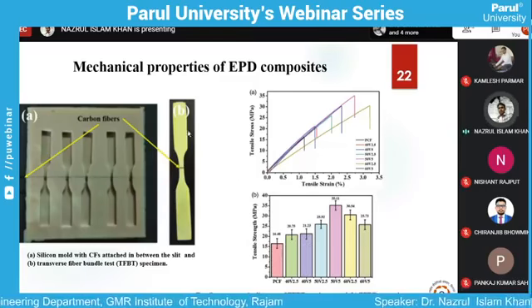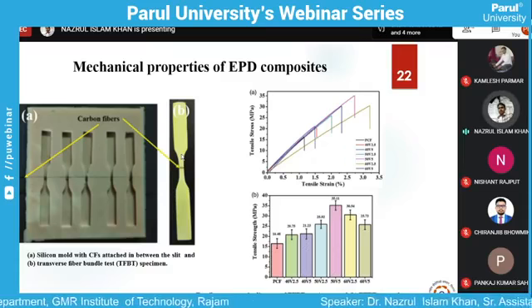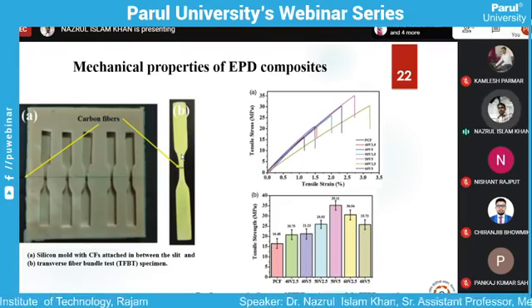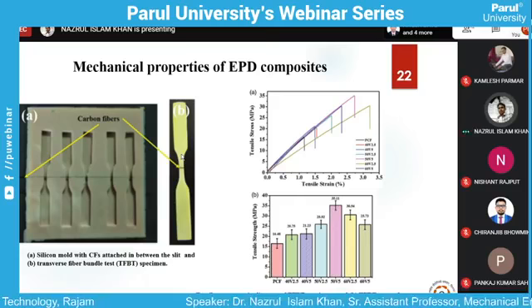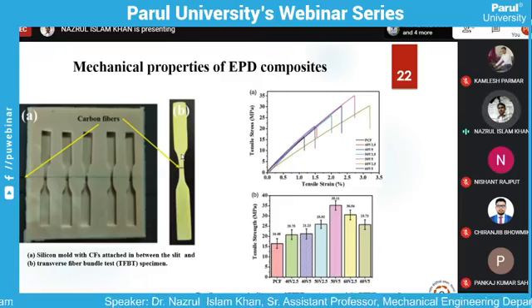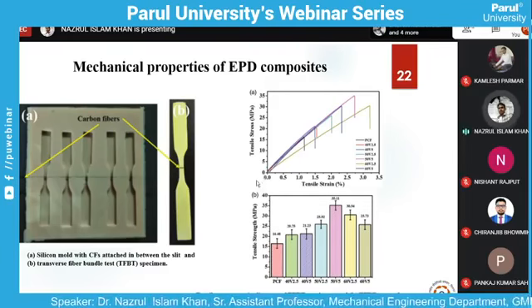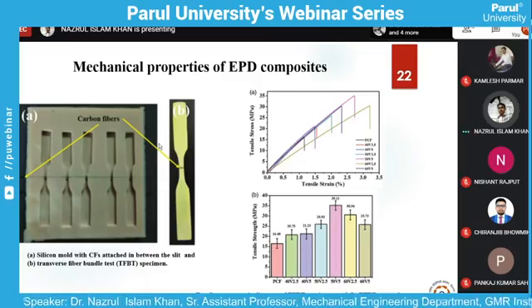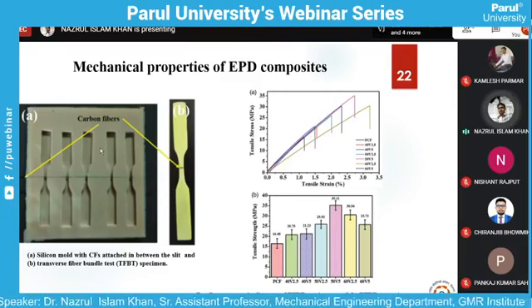At what extent you need this deposition of the nanofiller will depend on what the applied voltage is. If you increase the voltage, then you will get better deposition. Again, there is a limit. If you cross that limit, there is a chance that the fiber will get burnt, because you cannot add very high voltage. So to optimize that, you can play with the voltage and see, and correspondingly prepare the composites.